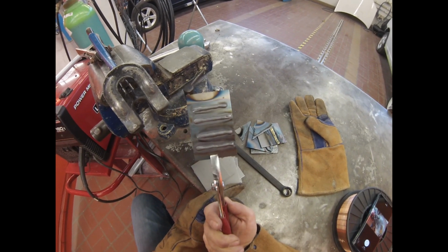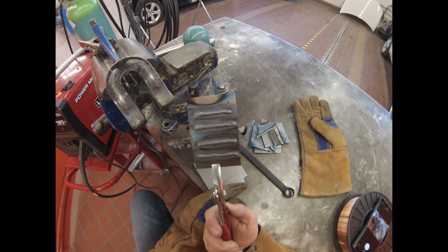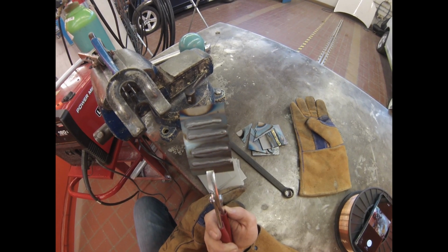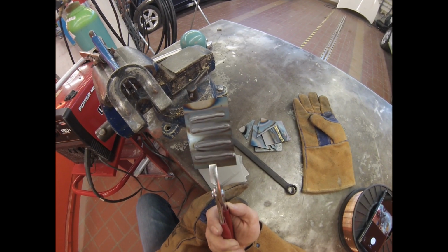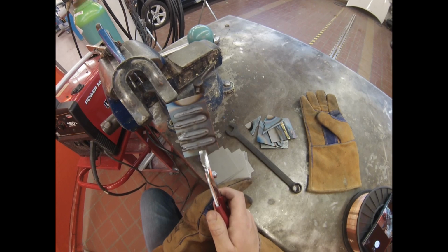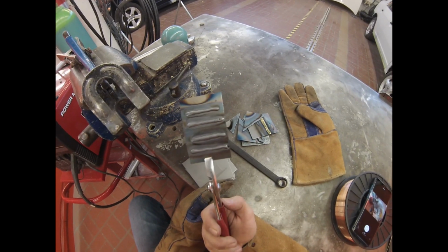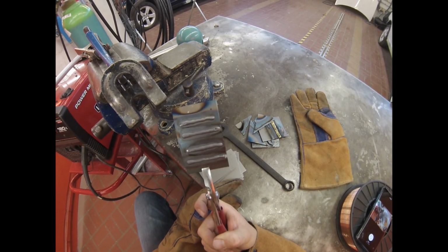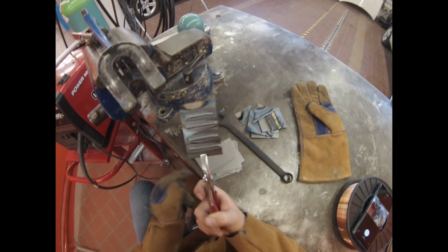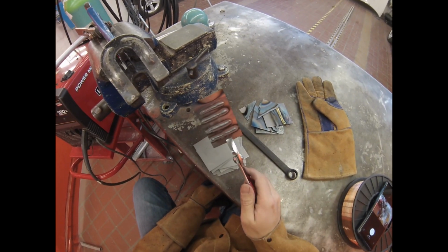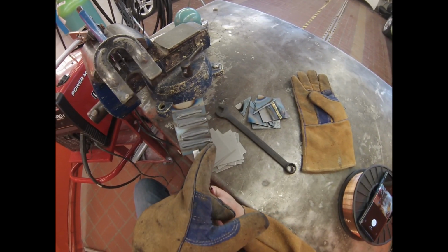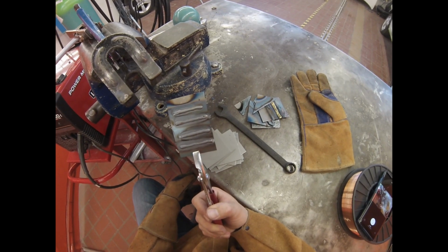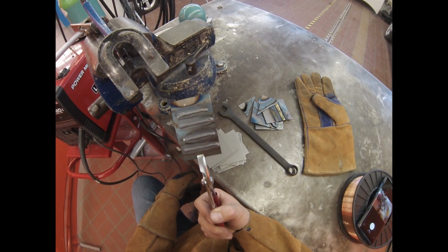But you can see the settings on that weld are actually pretty decent for the baseline cheat sheet. Not too bad, right? That thin wire, you can see the travel speed is quite slow because there's not very much electricity and there's not very much welding wire going in, so it's a little slow, right? But that's how we weld 20 gauge sheet metal, right? And then at the end there, you can see I welded too close to the edge, nowhere for the heat to go. It just blew a hole through, right?